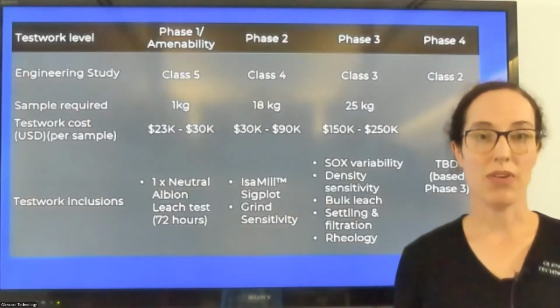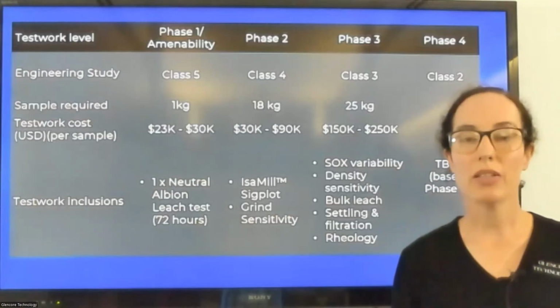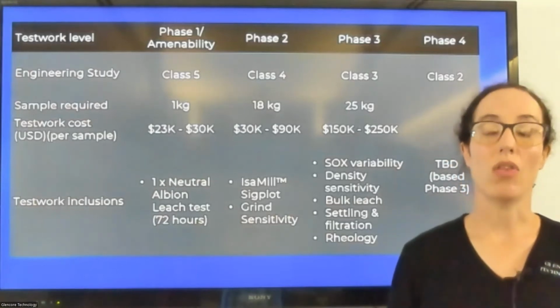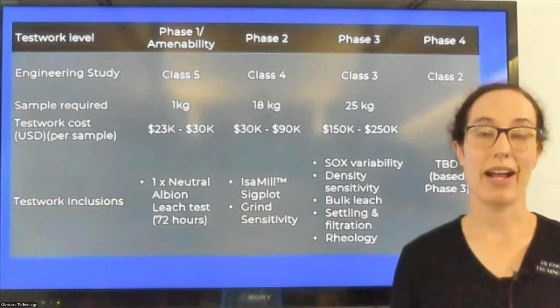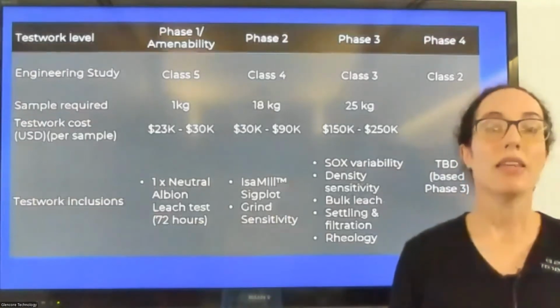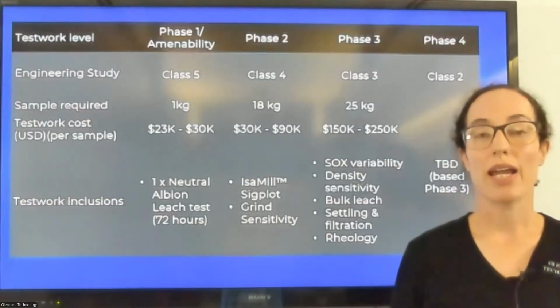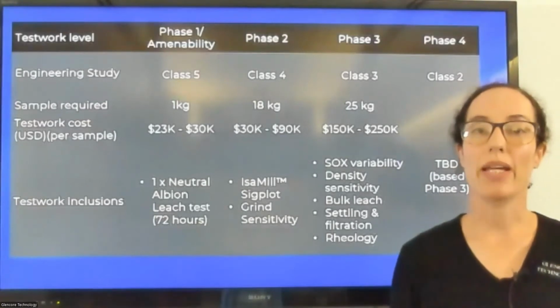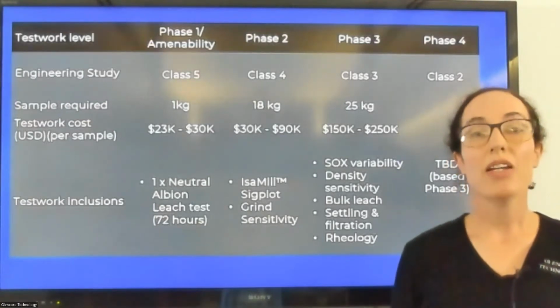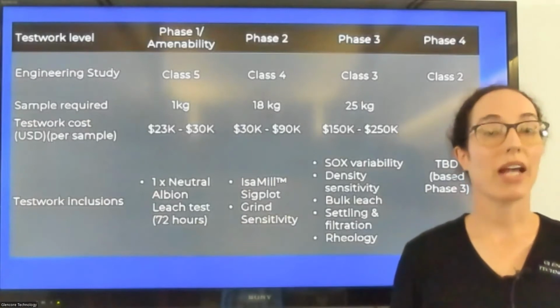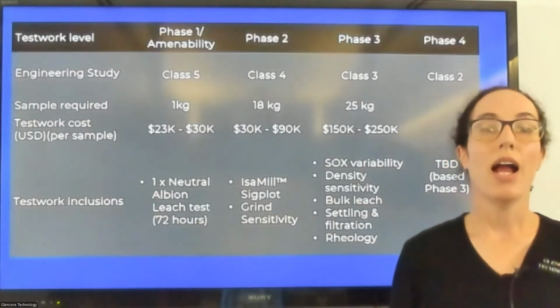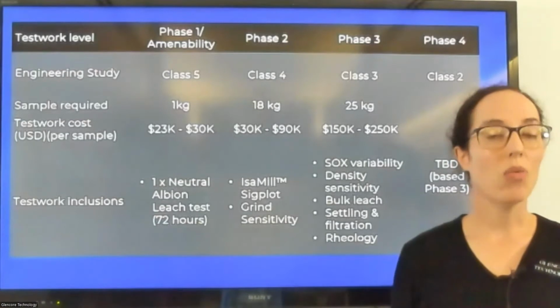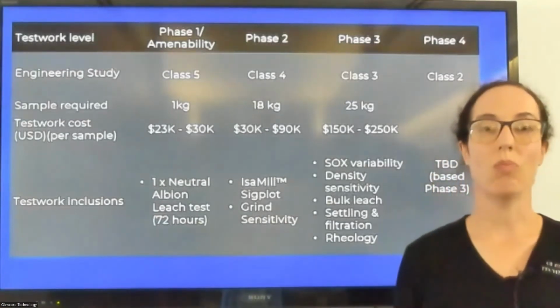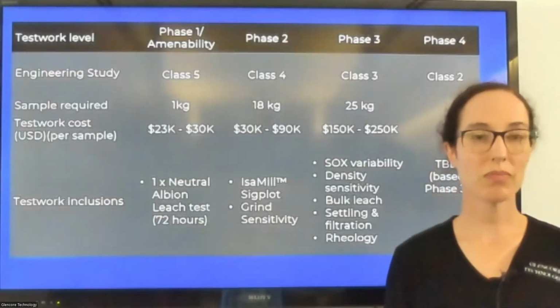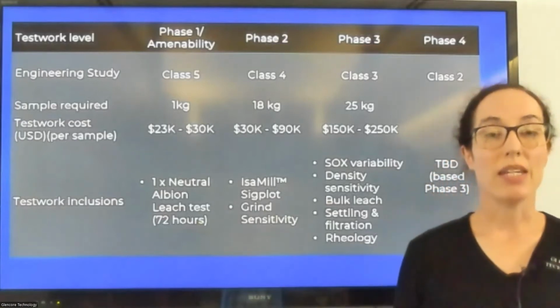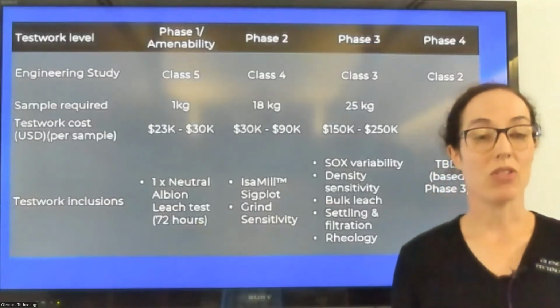If the test does fail, and by fail, I mean you do not get a good gold recovery on the Albion leach residue CIL test, then we'll know that there's something in the properties of your ore that does not make it amenable to the Albion process. An example of this could be that the gold is actually not hosted in sulfides, and therefore the Albion process does not open the sulfide matrix and make the ore more amenable to CIL. Then we step into phase 2.